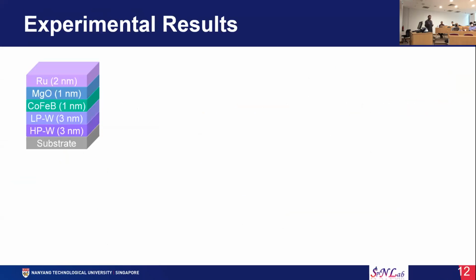Now I will show the experimental results. First, at the left, this is the schematic of the SOT thin film stack, where high pressure tungsten and low pressure tungsten is the spin orbit torque layer. CoFeB is our magnetic layer, and this is basically taken to get high spin orbit torque at low resistance level.